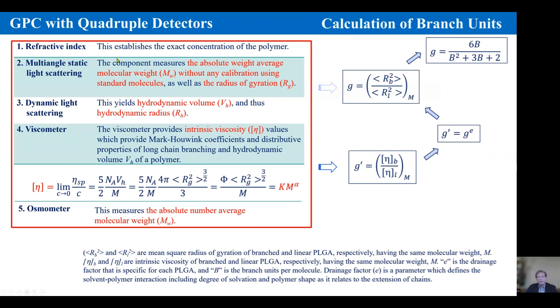First of all, you separate the molecules based on molecular weight, and then the number of branching, the B, can be calculated from comparing the square of the radius of gyration of branched PLGA compared to linear PLGA without branching. The radius of gyration of PLGA, the star shape, is always smaller because the multiple chains are attached to the core. So the radius of gyration is always smaller than the linear chain, and that's how we can calculate, based on a model, the number of branching from the core.